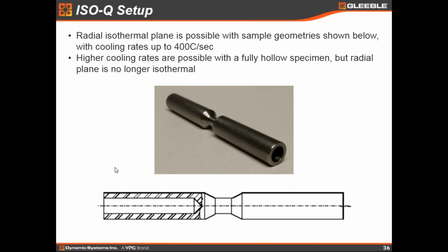But from some of the testing that we've done in the past, the isothermality of the radial plane is not maintained at that point, since you're going all the way through the sample. So to get really the best data you can get, it requires a little more work in that regard. We have an app note that I think I mentioned later on in this, that if you're interested, you can take a look at it and learn a little bit more about that.